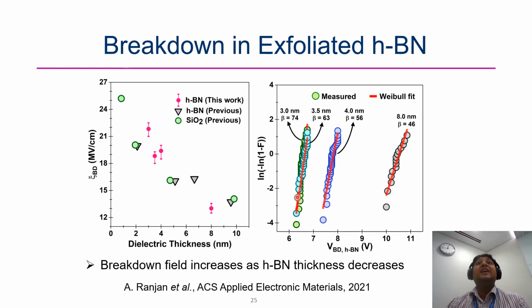This is unlike the case of CVD grown HBN. If you do the CVD grown HBN, you will see that the beta values are much lower, and this tells us that the CVD needs further improvement. Another aspect is that the beta values decrease with thickness. This is actually against the percolation model, because in conventional dielectrics, beta usually has a positive correlation with thickness. This also tells us that it would be the right time to investigate how these crystalline materials and the percolation model are correlated.